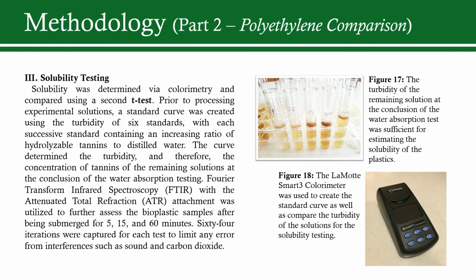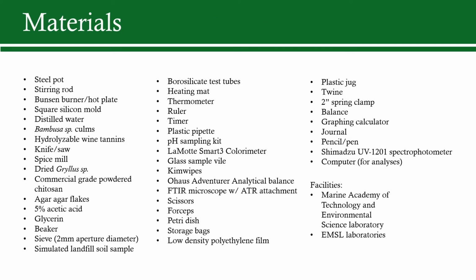FTIR was used once again to view any distortion and act as a secondary method of determining the percent solubility using an untreated sample as a comparison. 3 t-tests assuming unequal variances were performed between the biodegradation rates and water absorption and solubility percentages of the bio-based and polyethylene films. And here's a complete list of all materials.